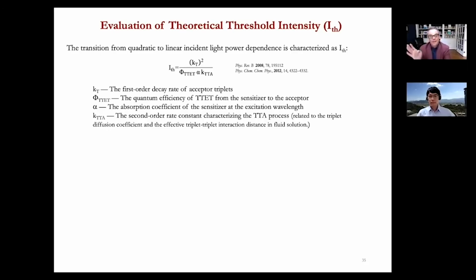Plus their zirconium is like 350 microseconds, but it's also a TADF molecule. So it's not quenched by trace oxygen as much as you would think either. So there's a lot of cool things about it that really make it special. And like I said, we were surprised. I did not expect this compound to behave this way. If I told you I expected that, I'd be lying to you. I never expected it to be the best sensitizer we've seen in 20 years. Never in a million years would I have thought that. But I do think eliminating all of the competing mechanisms is what is advantageous about using it. Okay. Thank you.